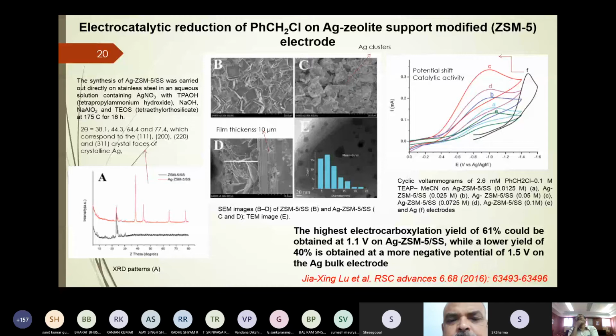If you compare F with A, B, C, D, it shows a shift in the onset potential towards the more positive side. This shows that this silver zeolite based electrode acts as a good catalyst for the conversion of this benzyl chloride.